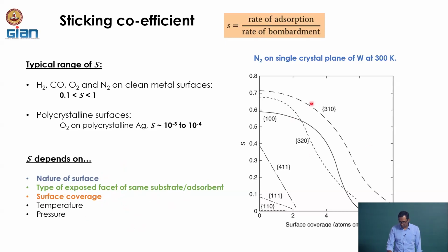And the first three, we are seeing an example here on the right hand side plot, where we are looking at the sticking coefficient on the y axis as a function of the surface coverage, which is given as atoms per centimeter square of the surface area, of nitrogen on different facets of tungsten at 300 Kelvin. And as you can see, we have tungsten 100, 110, 111 and different kinds of facets, and the sticking coefficient is different on each. But at the same time, the sticking coefficient is not constant throughout the surface coverage. As the surface coverage is increasing, of course, the number of available sites for taking up more gases is decreasing continuously, and that's why my sticking coefficient goes down as a function of increasing surface coverage, okay.